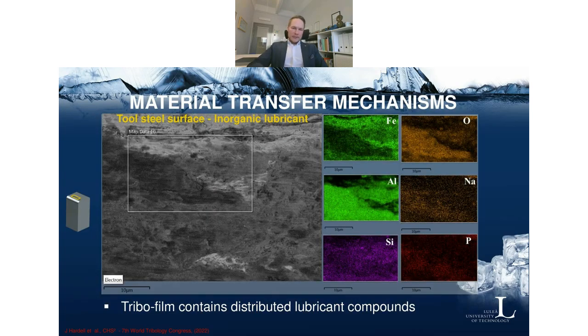Now, we did take a look at the surfaces afterwards, obviously, to understand what is going on. And what we could see here, now you have a micrograph showing a part of the surface where there is material transfer, and the EDS map on the right side. So you can see a lot of aluminium, and you can see where the iron is around that aluminium, but it also intermixed to some extent. But the lubricant compounds, or the elements belonging to the lubricant, they are concentrated where the aluminium is. So there is an intermixing of the lubricant constituents into the transfer material.